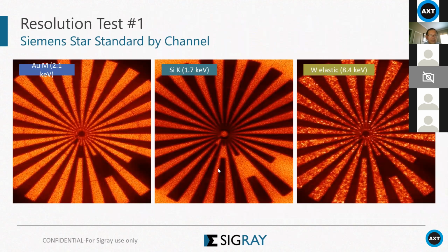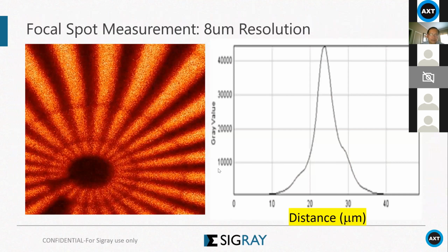This slide shows some scanning of a Siemens star resolution pattern. This sample is a gold microstructure. As you can see, we can see resolution down to a few microns. The next slide will show that. The curve on the right is a line scan across one of the lines, and you can see the focal spot is about 8 microns.